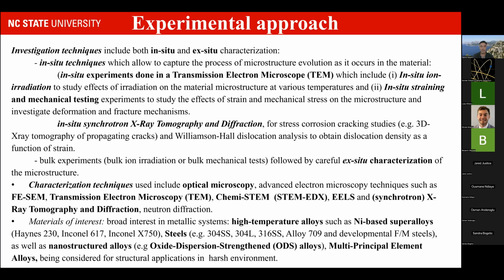And in terms of characterization techniques, I use a lot of electron microscopy and, as I mentioned, synchrotron XRD and tomography. But the materials of interest in our group have revolved around high temperature alloys, essentially metallic systems with nickel-based alloys such as Haynes 230, Inconel 617, Inconel X750, steels, the 300 series, development steels such as the 709 steel, and developmental ferritic martensitic steels. There's a very particular interest in nanostructured alloys, such as oxide dispersion strengthened steels and nickel-based alloys, as well as more lately, multi-principal element alloys, known as high entropy alloys. So all for applications dealing with extreme environments.